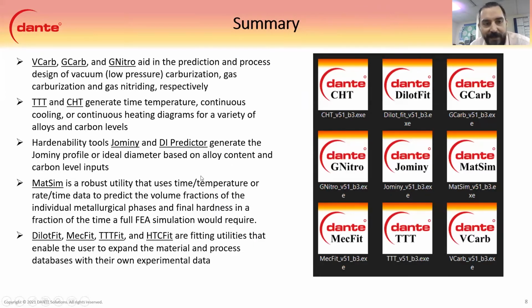Mat Simulator is actually like a 1D DANTE simulation. It's a robust utility: you input your time-temperature or your rate-time data, and you can predict the volume phase fractions over time, the individual metallurgical phases, and final hardness, which is really useful in seconds compared to a full FEA package because you're only solving for one node.